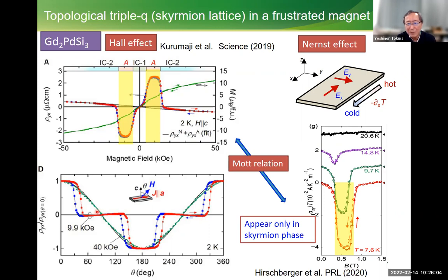One more important point, we cannot afford to describe the detail, but this topological Hall effect also shows up in the thermoelectric effect. Some people are very interested in the transverse thermoelectric effect termed the Nernst effect. You just apply the thermal gradient, temperature gradient, then the thermal flow occurs. But in contrast to the longitudinal thermoelectric effect, namely the Seebeck effect, we observe the Nernst Hall effect. And this also showed a very gigantic response around here. And this is alpha xy divided by T.